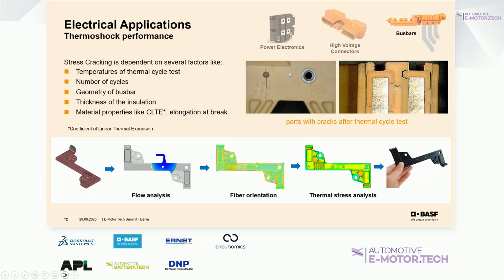What we made here also is we deeply involved our simulation department, and we developed our own material model where you could simulate at the beginning the typical flow behavior of the injection molding process, take the fiber orientation out of that, and based on these two pieces of information and many more measurements we did, make a kind of thermal stress analysis and see, okay, where might be an area which is critical, or where is it uncritical in terms of thermoshock performance.